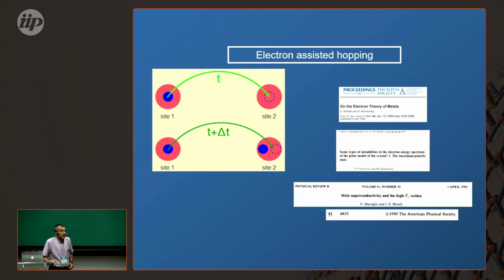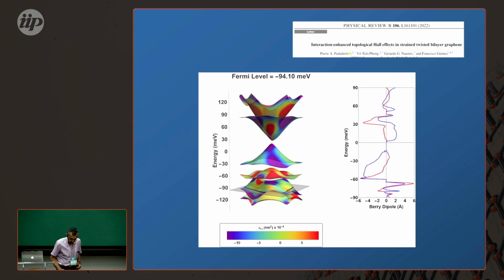the Hubbard model just in its canonical form. I do agree that one needs to take into account assisted hopping in the Hubbard model, probably because that just implies that the wave function of the orbitals you include may change with the amount of charge you have in them. I'm not sure if that explains high Tc, but I'm sure that twisted bilayer graphene is a very clear example where this situation happens - it's a very extreme case.